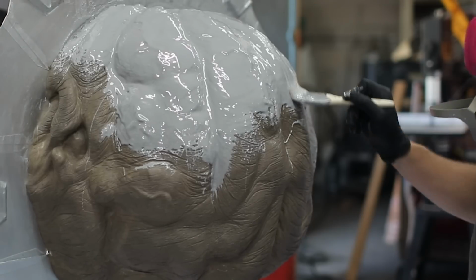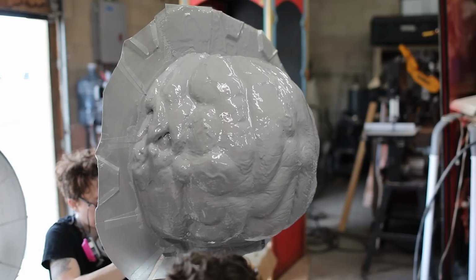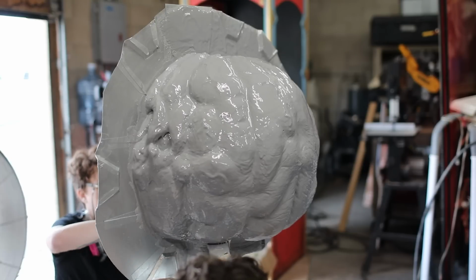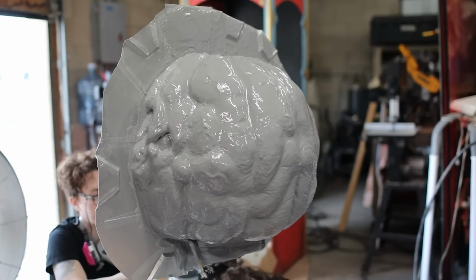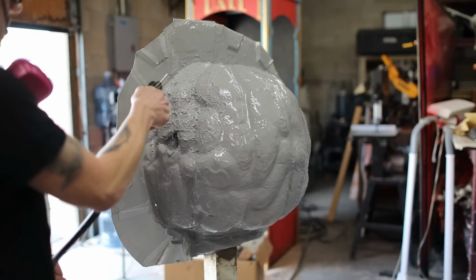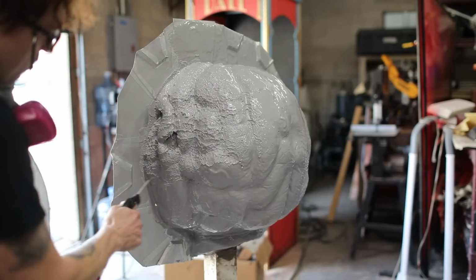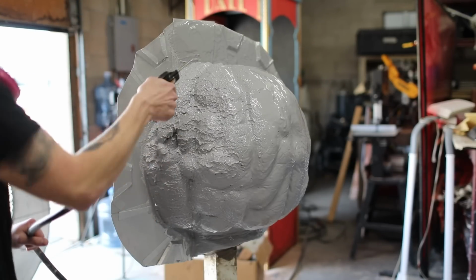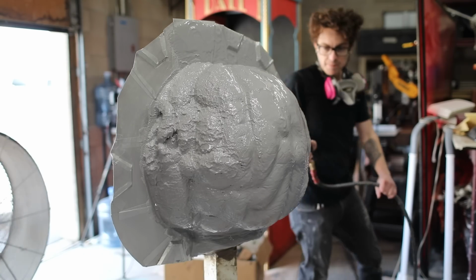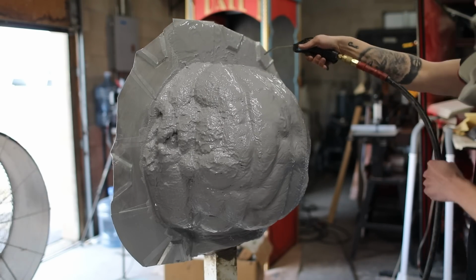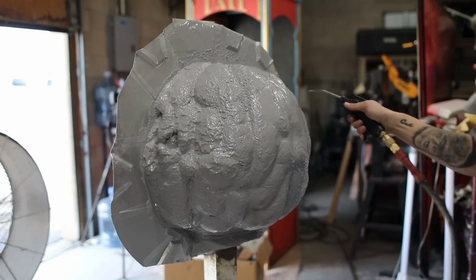Now with the detail layers, this is where you've got to make sure there are no air bubbles trapped inside any of the nooks or in the teeth, right? Fine details. You're going to get little air bubbles everywhere, and those will show up in your final casting, and you'll have to remove them. So we brush on our epoxy coat, a thin layer, and then we use the air compressor to blow the epoxy coat into the crevices and in the details, making sure there are no bubbles. Applying this coat, you really have to keep in mind where bubbles might get trapped.